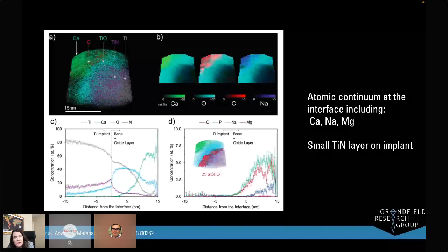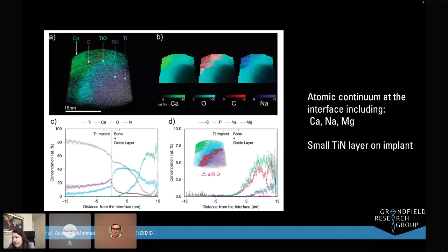We also see sodium and magnesium in high concentrations at the interface, and we really have this atomic continuum. We don't have an abrupt interface where the bone stops outside the oxide layer. Rather, we have a penetration of the two layers together.